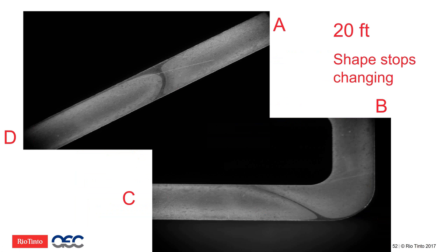Okay, this is 20 feet. In that exercise, that profile, and we did many different profiles in this case, but at 20 feet, that's quite a bit of metal here, actually. Finally, on all ports, the transverse weld was fully removed. That means that all the metal from the previous billet that was inside the die was finally pushed away, and the new billet was finally being extruded.